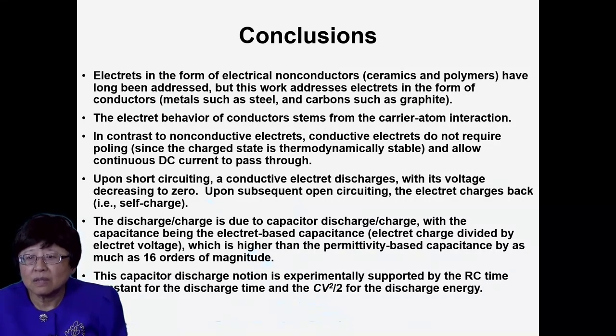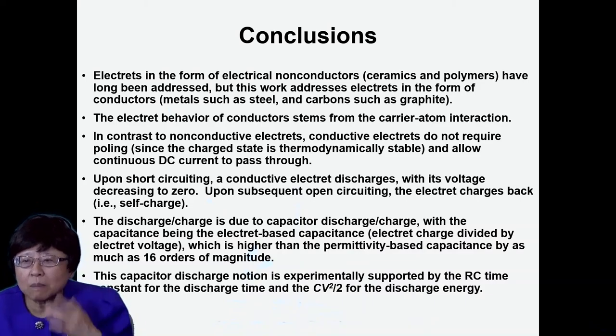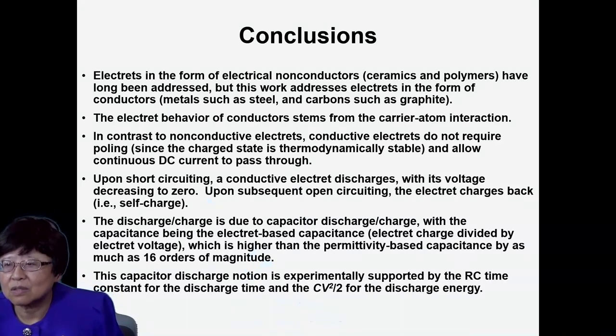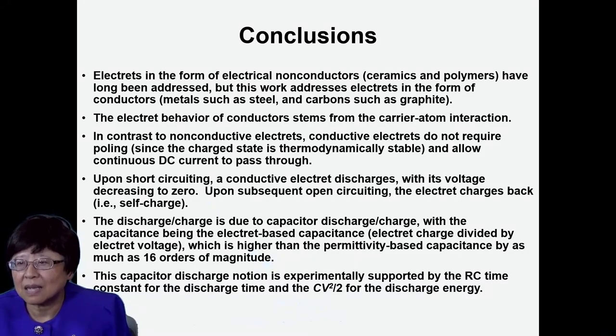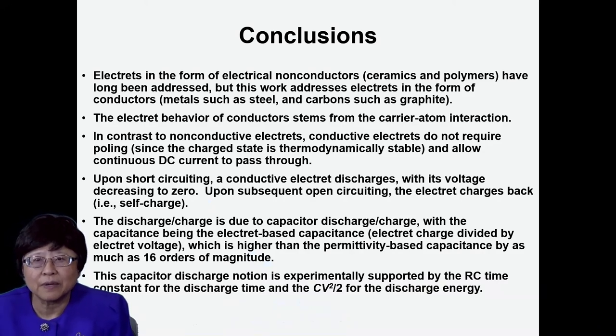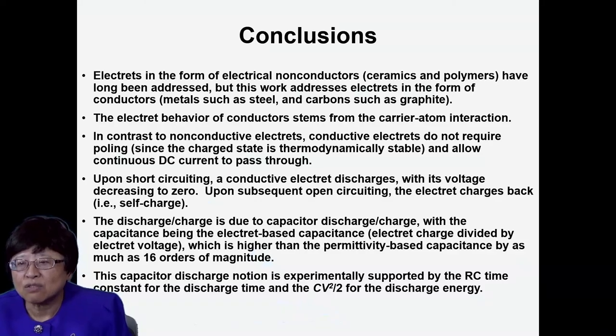Here is the conclusion. The electrets in the form of electrical non-conductors, ceramics and polymers, have long been addressed. But this work addresses electrets in the form of conductors, metals such as steel, and carbons such as graphite. The electret behavior of conductors stems from the carrier atom interaction. In contrast to non-conductive electrets, conductive electrets do not require poling, since the charge state is thermodynamically stable, and they allow continuous DC current to pass through.